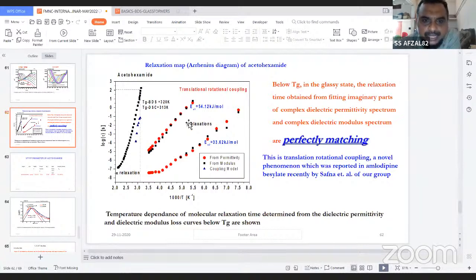from the conductivity relaxation. That is, conductivity relaxation is the translation of ions, and the dielectric spectrum is only due to the dipolar relaxation or the orientational polarization of the dipoles. So if I am getting the same time and the same temperature, which means they are superimposing in the glassy state, that means in the glassy state, there is a coupling between the translation motion and rotation motion.